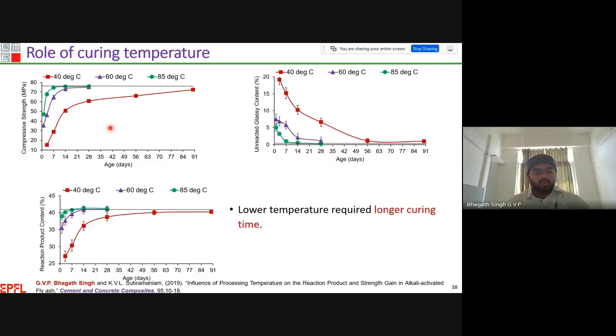We would like to use only pure fly ash, so that we can control the other parameters. Then, if you look at the unreacted glassy content and the reaction product content, the compressive strength is proportional to the reaction product and inversely proportional to the unreacted glassy content. In all these three mixes, everything is the same; the only variable is the temperature.